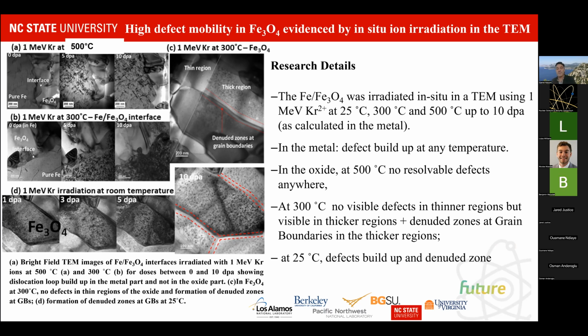And we really started looking at the literature and started wondering what could be intrinsic to the magnetite that would impede the formation of defects. But what we observed during the experiments, especially at 300 C, by looking at all the different regions, is that there was an effect of thickness. In fact, only the thin region did not show defects. Wherever you have a thick region, you would see defects forming in the oxide.